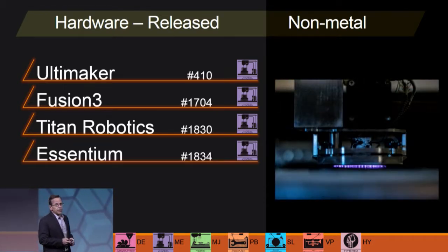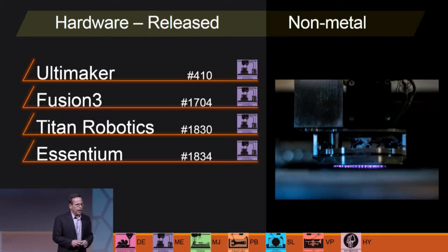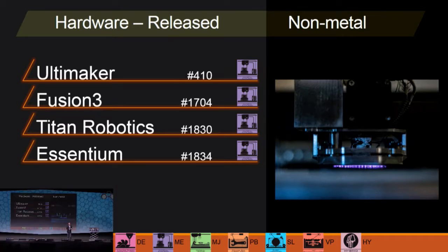Essentium, it's actually Essentium Materials, has come out with a machine called the HSE, high speed extrusion. They're picking up most of their speed not by a bigger orifice and dumping more material through, but by faster tracking of the deposition head across the XY area. This one's interesting because they have patented technology that prior was a bolt-on to be added onto other people's equipment. It's called flash fuse. They're using a material that's coated with nanoparticles, and then they're imparting, as you can see the little purple area, they're using plasma to send an electrical charge which activates that coating of the nanoparticles, which creates localized heating, which increases the Z-bond strength. Also with this, they're claiming about 10 times performance increase based on other material extrusion systems.